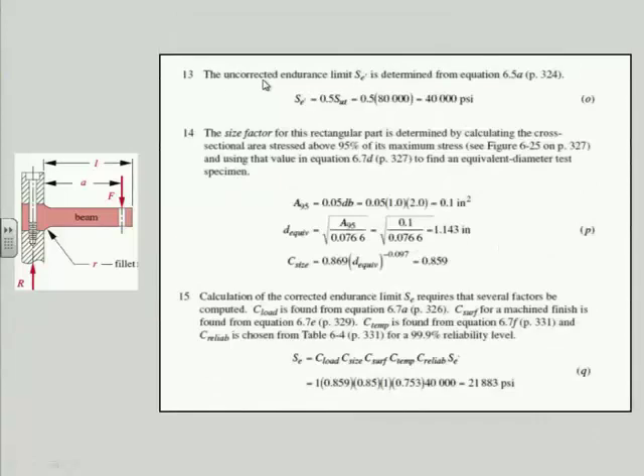Now I got to look at my material, and I got to get the endurance limit. So we go through the usual rigmarole. Take half of the SUT. That's 40 grand. I don't have a round part, so I got to use a trick to relate this rectangular thing to a round part. The trick says, take the area that's subjected to 95% to 100% of the stress in the cross section, which is just the outer rim of the top and bottom. We only care about the tension side anyway, which would be the top in this case.